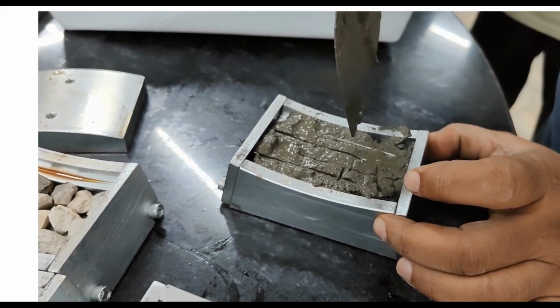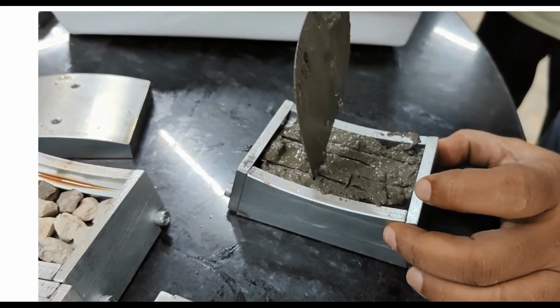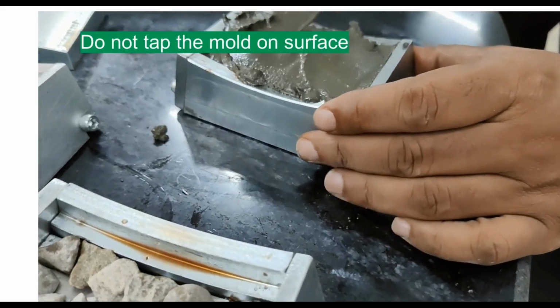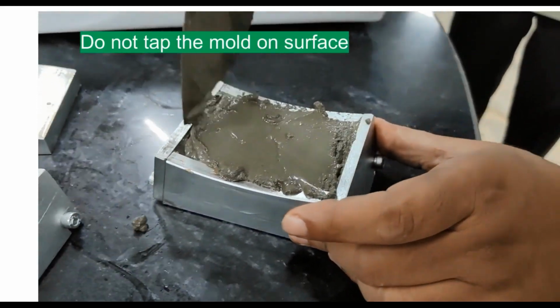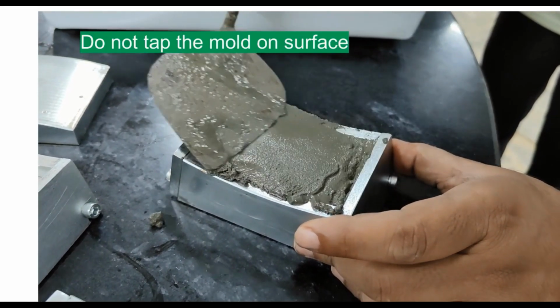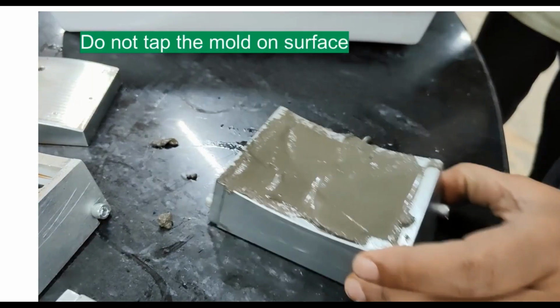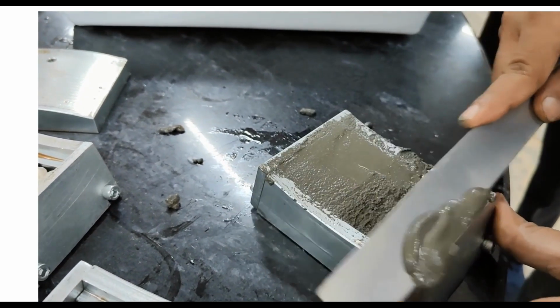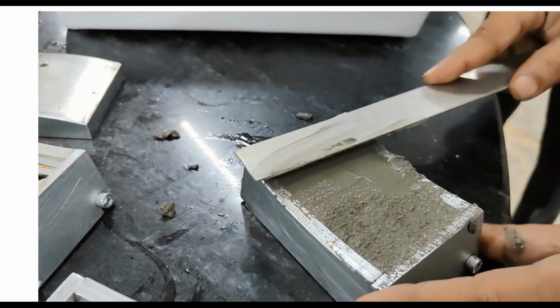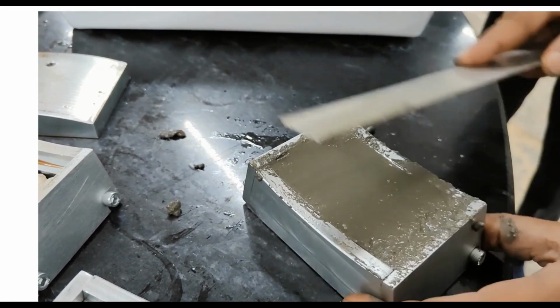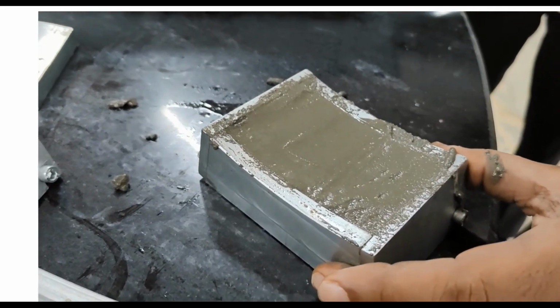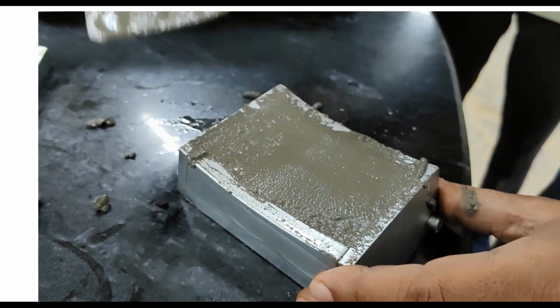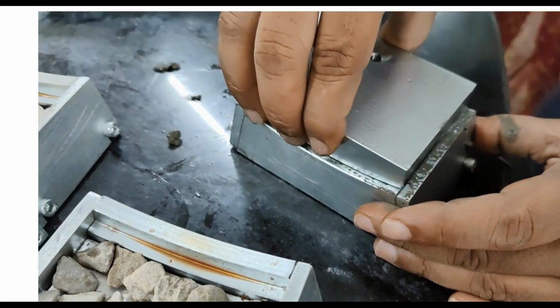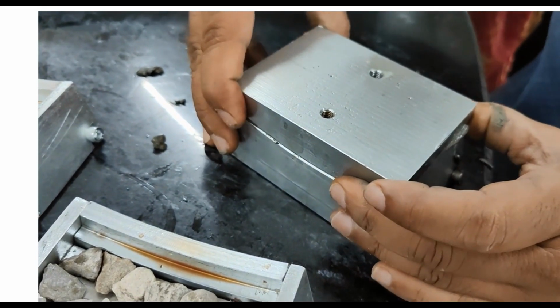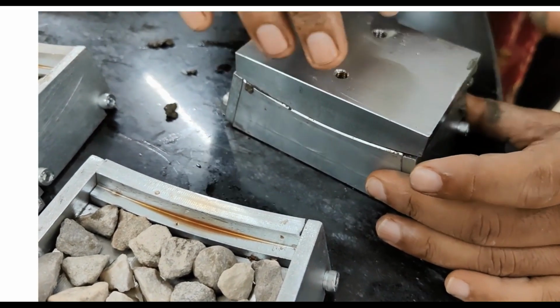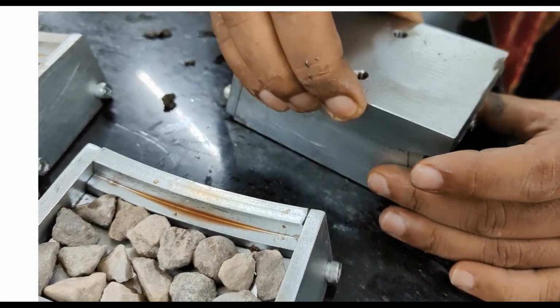Now make the surface smooth by putting some more paste here and using a flat edge of a knife or a scale to make the surface smooth. Then you can use the cover of the mold also to give a perfect shape to the specimen. Do not tap the sample, otherwise the cement slurry can go below the aggregates, and then these samples can be taken out from the mold. That is how you can just put the cover of the mold to give a shape.